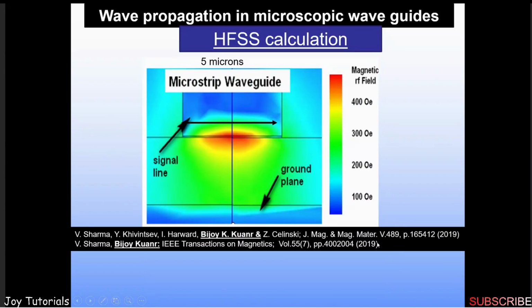So just going through a few more HFSS calculations, and what you can see here is from HFSS, the high frequency simulator calculations. We can see that the electromagnetic field just below the signal line can go up to even 300 to 400 Oersted. It's a huge field to make high power devices.